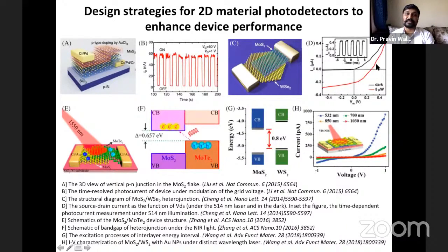So this performance can be controlled, and here you see in the inset of the figure, current versus time, and you find this response is very fast, right? So the responsivity is quite good. The speed of this kind of two-dimensional photodetector is improved just by making a sandwich of two different 2D materials on each other, right, and the performance has improved drastically, right? So this is in milliseconds, you see 0 to -3 milliseconds, and this was in seconds, right? So as compared to that, this strategy has improved the speed, or you can say the responsivity has been improved.